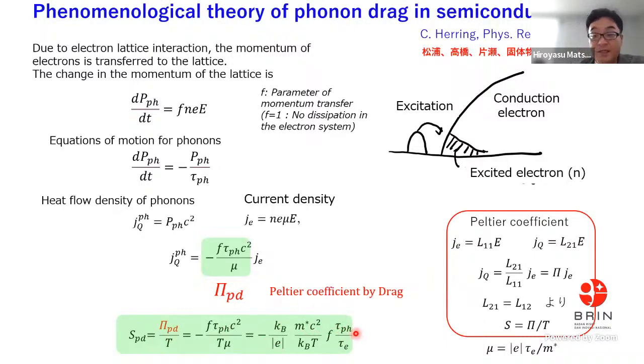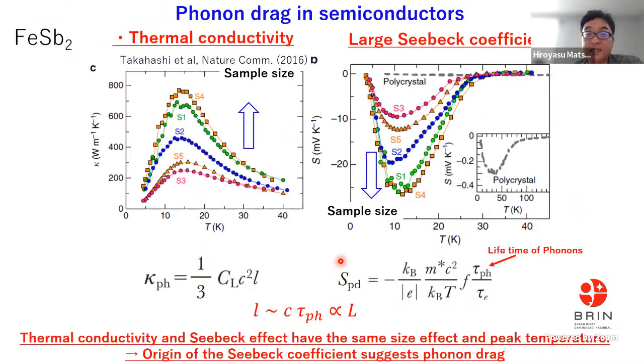Tau phonon means the relaxation time of phonons. So when we see the experimental result, this is the experimental result of iron antimony 2. We have the peak at low temperature. This is the Seebeck coefficient, and the peak at low temperature is coming from the phonon drag. And the important point is that we have the sample size dependence.